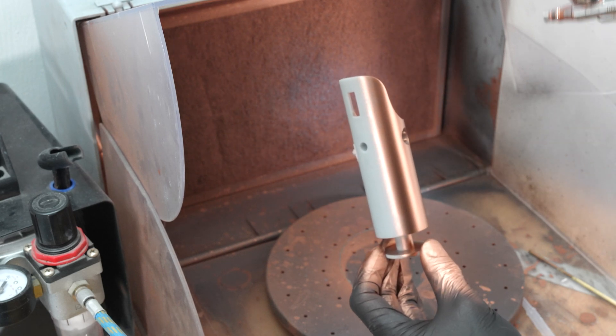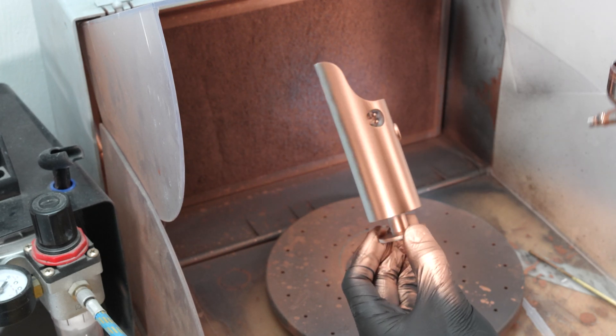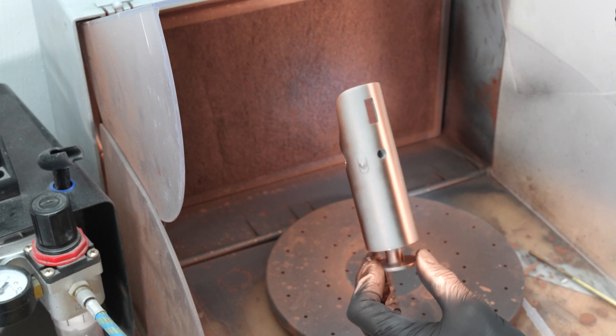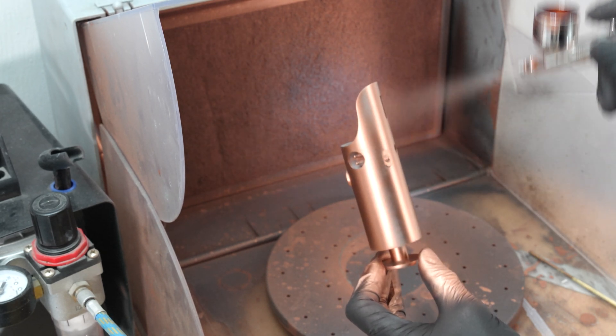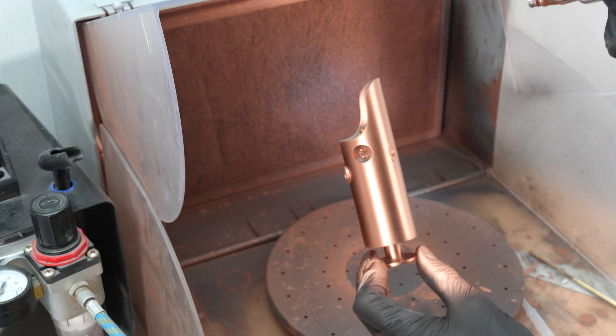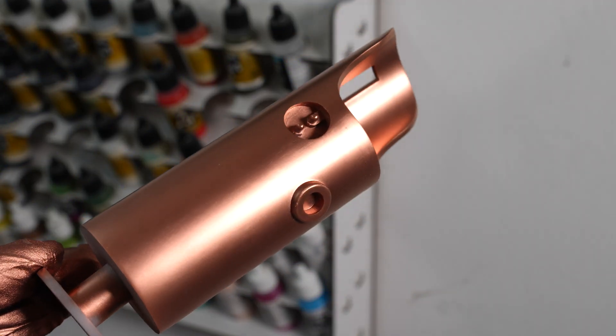Spray very gently with about two bar of pressure. It's better to apply multiple thin layers instead of one thick layer. After you've sprayed everything, it's best to let it dry thoroughly for a few hours.